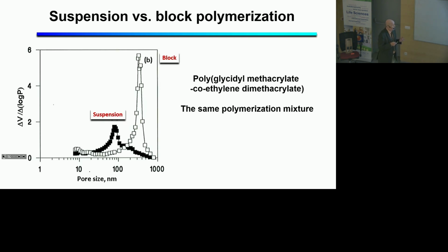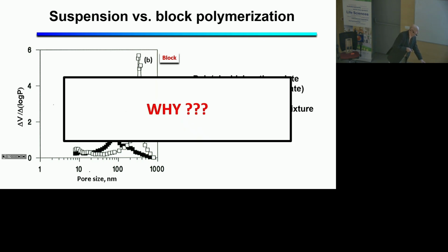So what we did, we used the same polymerization mixture consisting of glycidyl methacrylate and ethylene dimethacrylate. We prepared particles and we prepared the monolith, and then we measured the pore size distribution. To our big surprise, we found that they were not equal, although the polymerization mixture was the same for both applications. So we were really scratching our heads, asking how come the same polymerization mixture gives two different pore size distributions. And, well, we were thinking how to explain this.